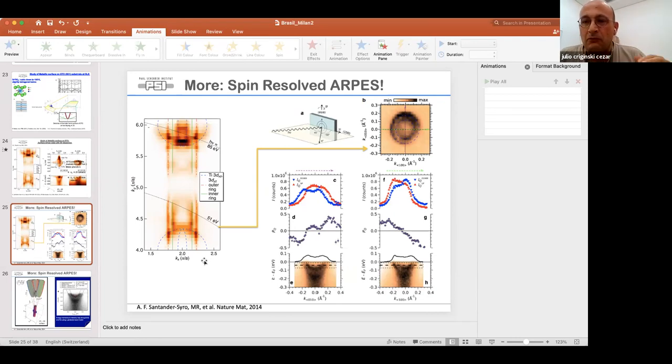The first is, how much longer is a spin detected ARPES compared with a normal ARPES? And the second question is, if you play with the polarization of the light using this spin detection. Yeah, very good question, Julio. So it's true, the efficiency of the spin resolved ARPES, or let's say the Mott detection system, is very low. There are two drawbacks because of that. First, you need to use a large opening of the slit and increase the flux, so the beam is largely shining over the sample, and any inhomogeneities will spoil the measurements. So you need to have a very good quality of the crystal.